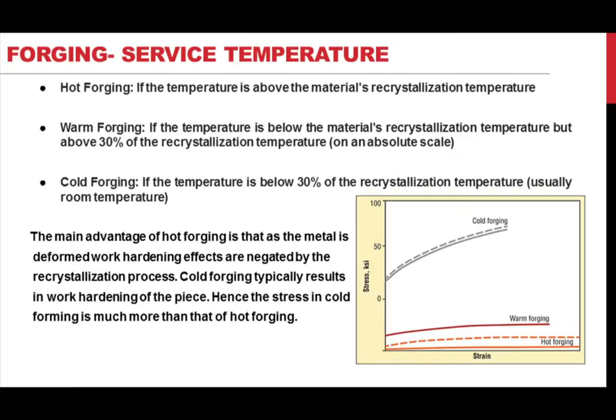For hot forging, the temperature has to be above the recrystallization temperature, which is defined as the lowest level of heat at which the distorted grain structure of a metal is replaced by a strain-free grain structure. For warm forging, the temperature is below the material's recrystallization temperature but above 30% of the recrystallization temperature on the absolute scale. Whereas for cold forging, the temperature is below 30% of the recrystallization temperature, usually room temperature.